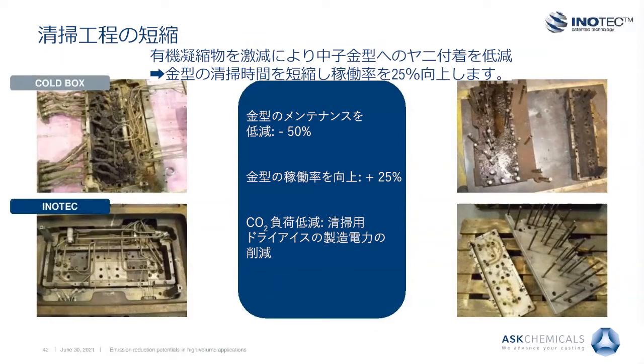When casting with inorganic sand cores, this costly and energy-intensive cleaning step is reduced by more than 50%. As a side effect, permanent die mold casting processes with inorganic bound sand cores are operated at lower temperatures compared to casting processes with organic bound cores, leading to a higher die mold availability of 25%.